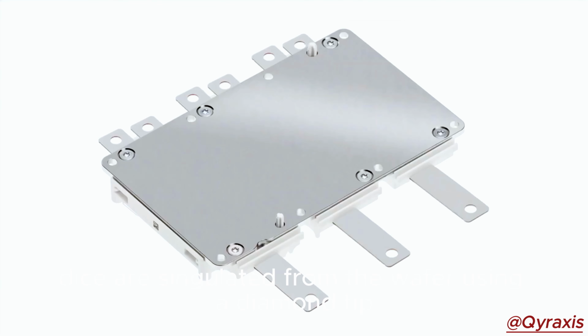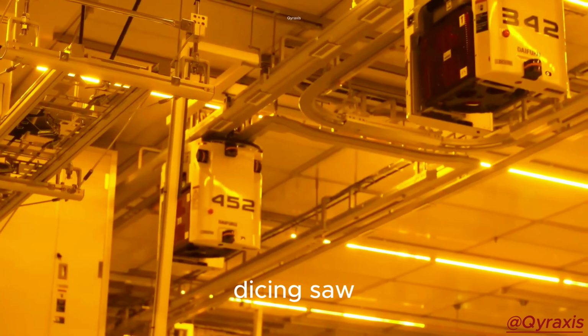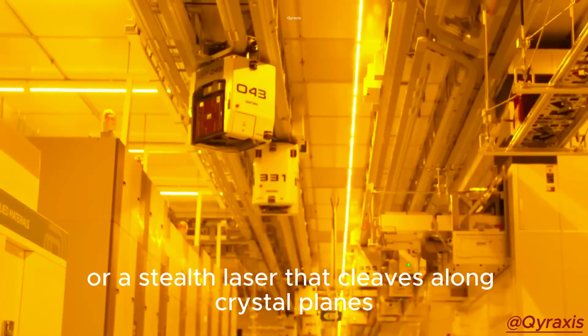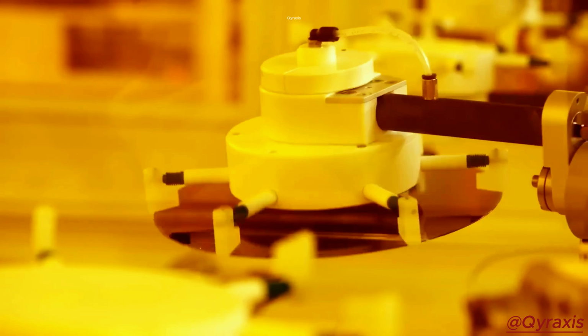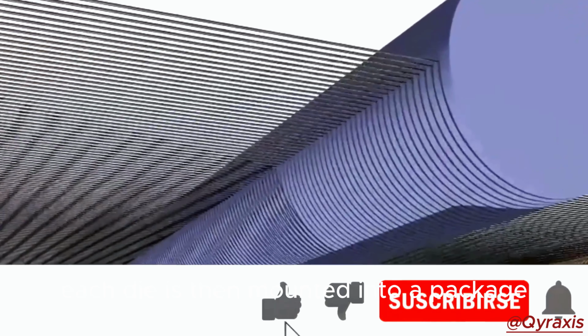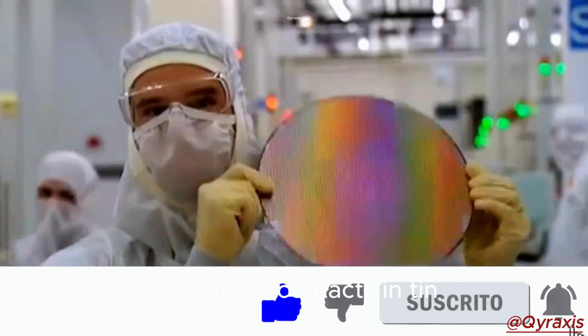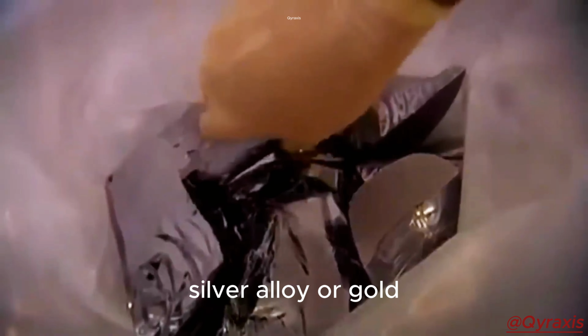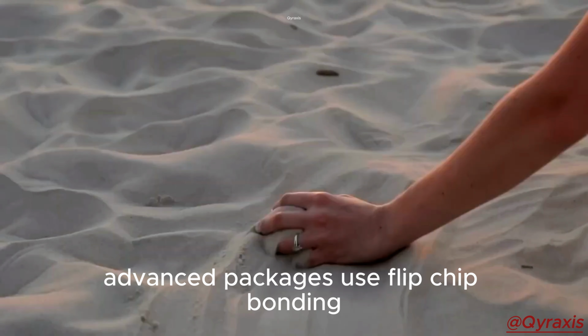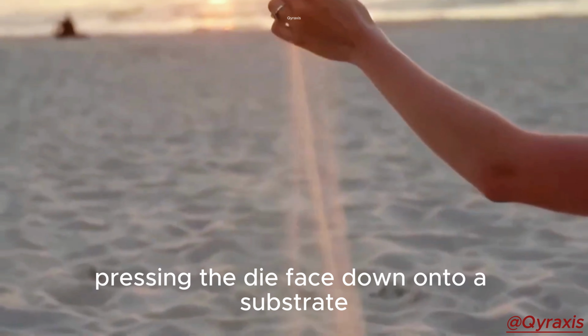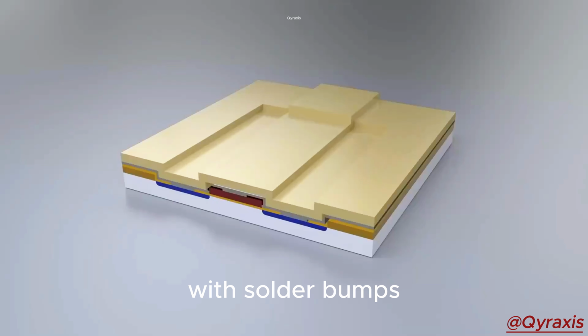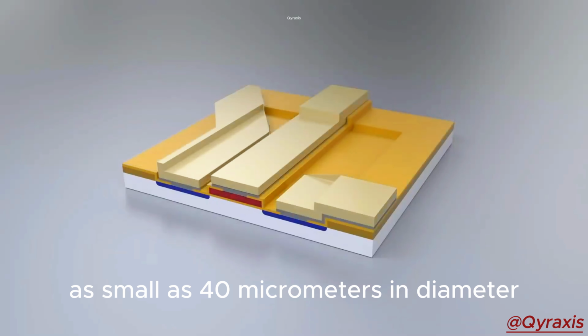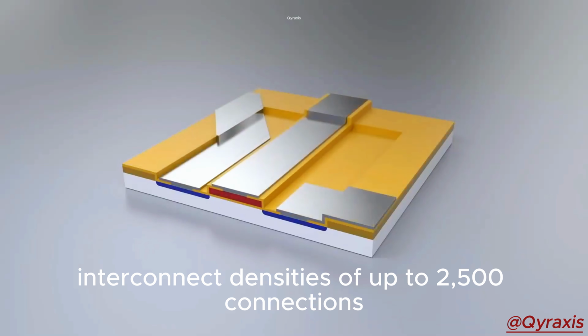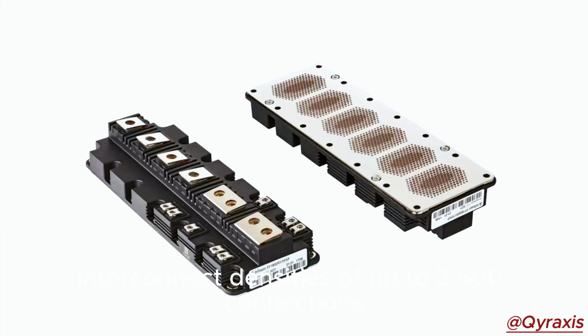Passing dies are singulated from the wafer using a diamond-tip dicing saw or a stealth laser that cleaves along crystal planes. Each die is then mounted into a package, a protective housing of molded epoxy with metal contacts in tin-silver alloy or gold. Advanced packages use flip-chip bonding, pressing the die face down onto a substrate with solder bumps as small as 40 micrometers in diameter, achieving interconnect densities of up to 2,500 connections per square centimeter.